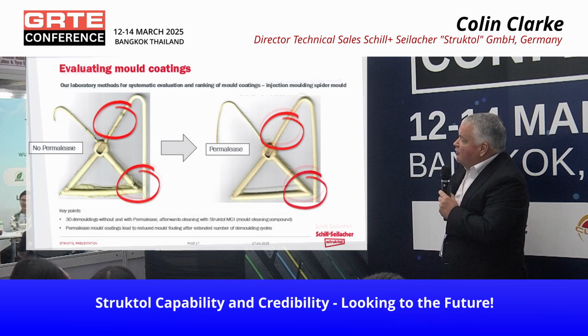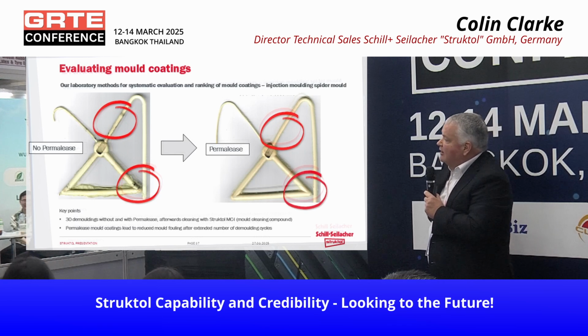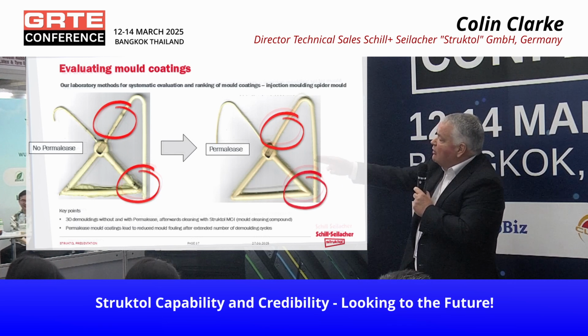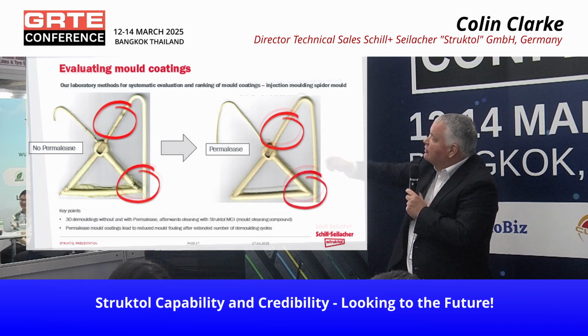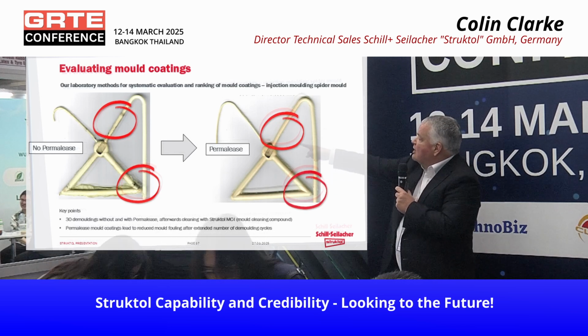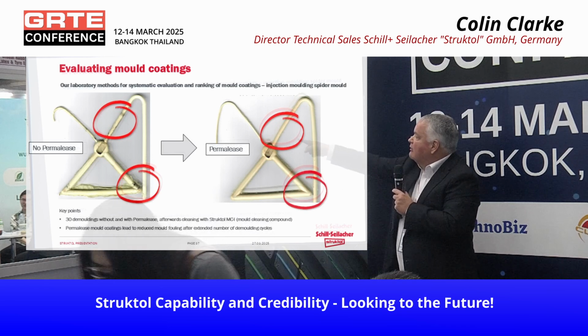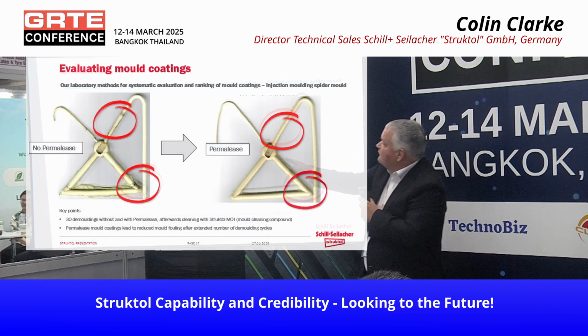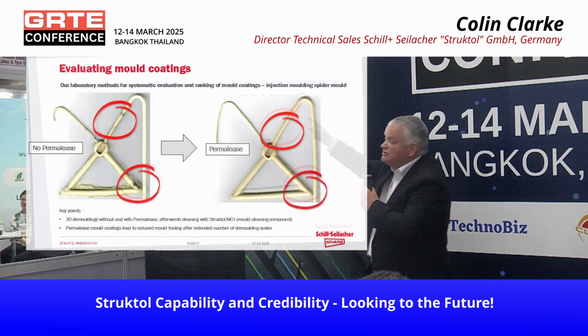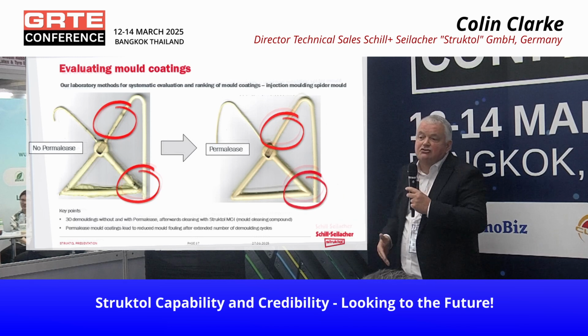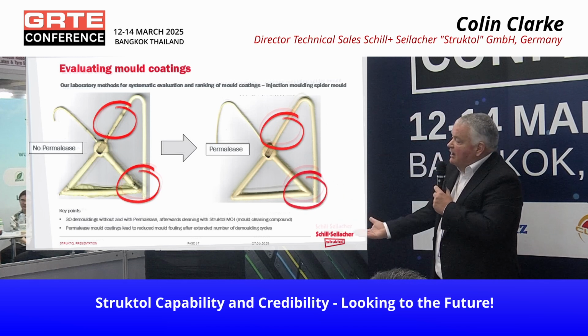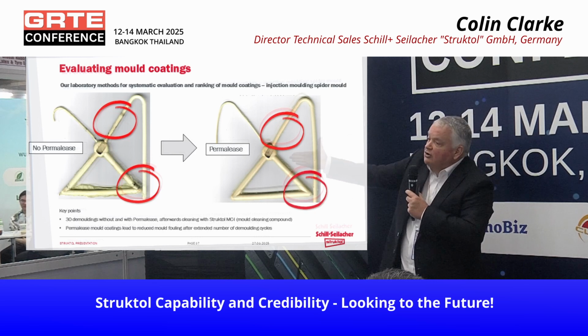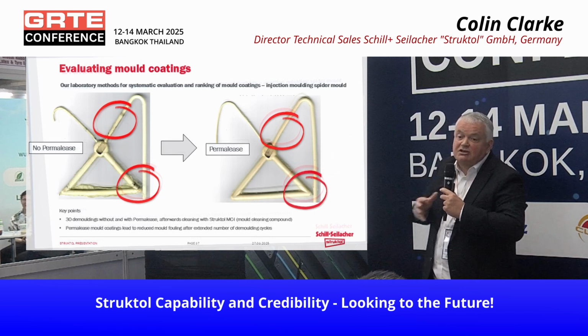We can see the performance in terms of reducing mold fouling. So that's an injection molding, the spider mold, with a high degree of mold fouling. The same coating, a very clean mold, we don't have mold fouling. We improve the flow. You see the flow increased much more because of the reduction of friction due to the coating. So better flow, better release, and a reduction of mold fouling by using the coating is possible.